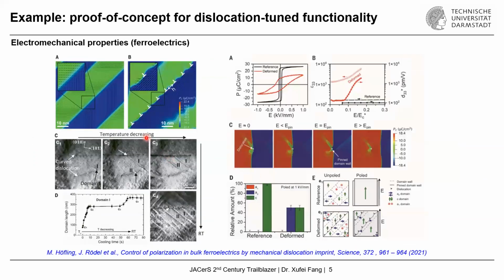For example, here I showcase the example of using single crystal barium titanate deformed at high temperature, where we can introduce dislocations. And this has helped to improve the large-signal piezoelectric coefficient d33* by almost 19 times. This is mainly due to the dislocations we imprinted in the first place, which pinned the domain walls and helped to enhance the electromechanical properties. Due to time constraints, I will not go into the details, and I would like to recommend you read this paper from our ceramics division.